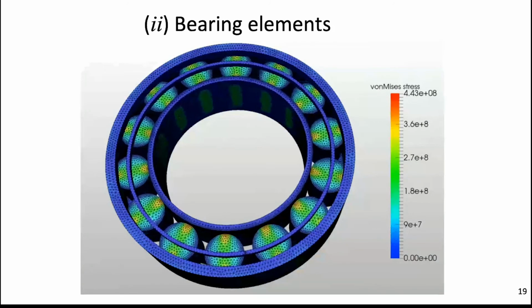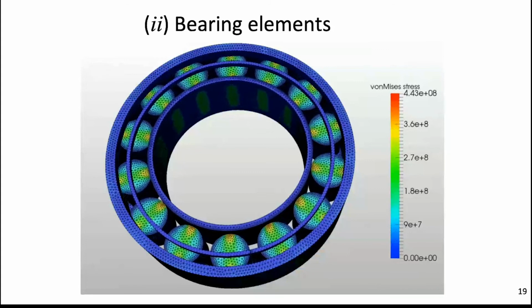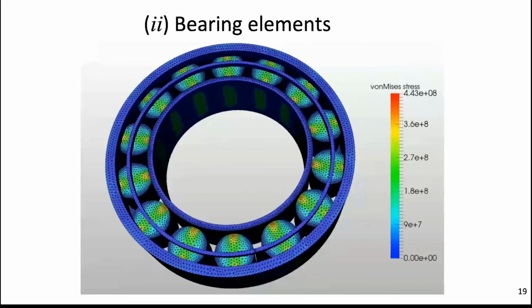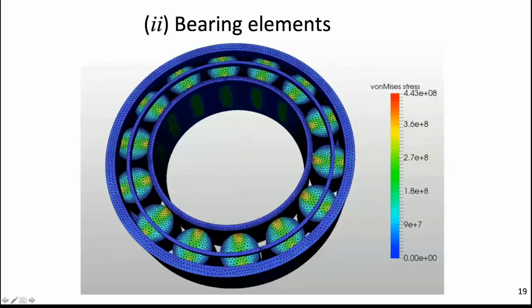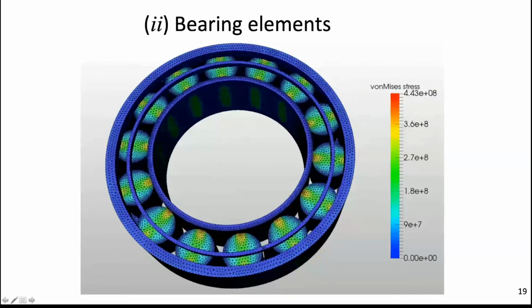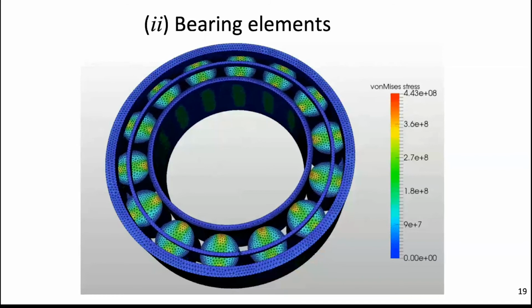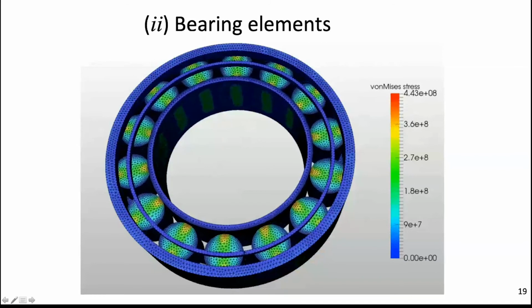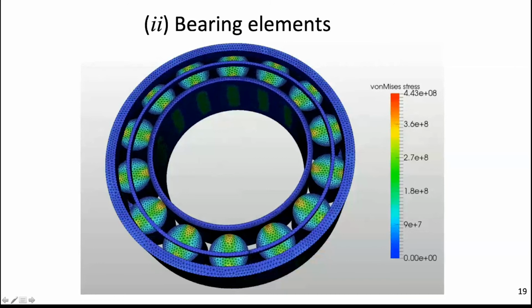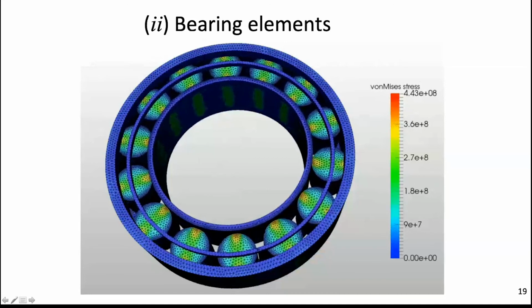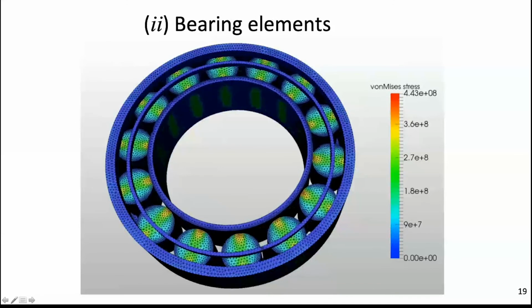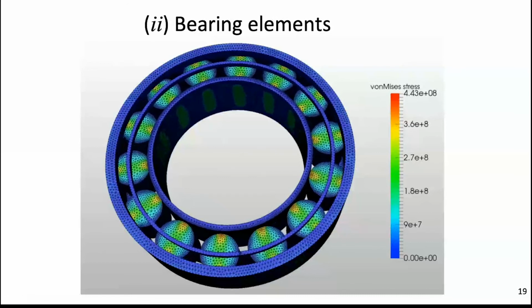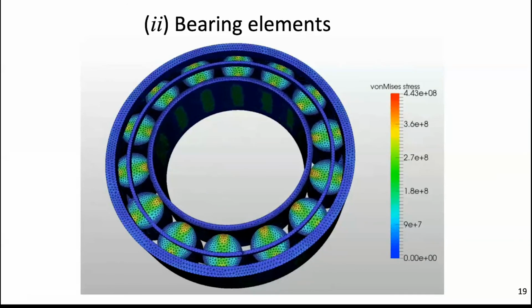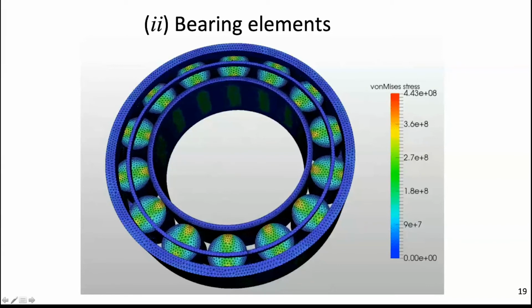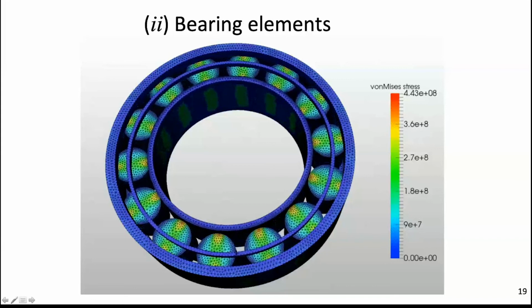The second example, as I already outlined, is that of bearing elements. Bearings are really interesting components because, as you can see here by the rollers, the color represents the stress to which the rollers are subjected. Red represents very high stress and blue represents low stress. Of course, the points in contact are the ones that experience a lot of stress. But what is interesting is that at the center of the roller, there is very little stress. However, all the bearings that are produced nowadays are solid. All the rollers are solid and the bearing rings are all solid.